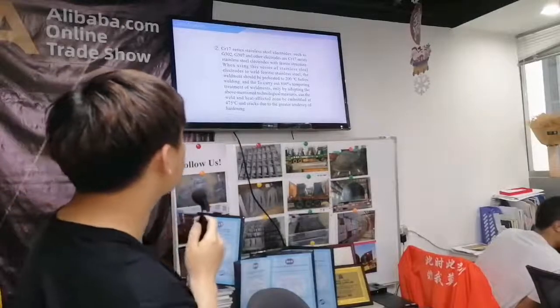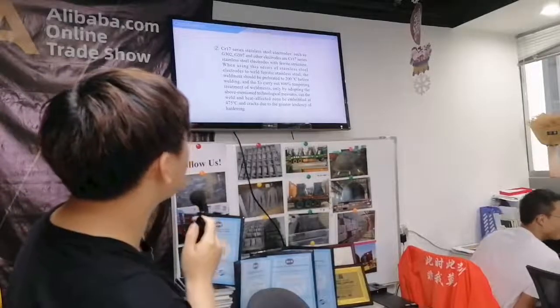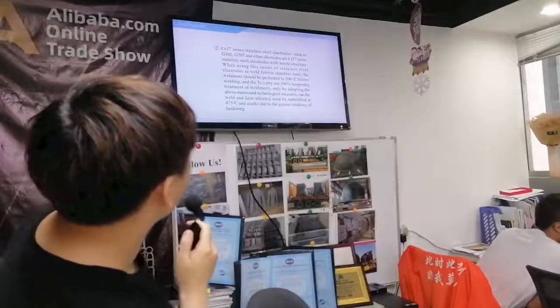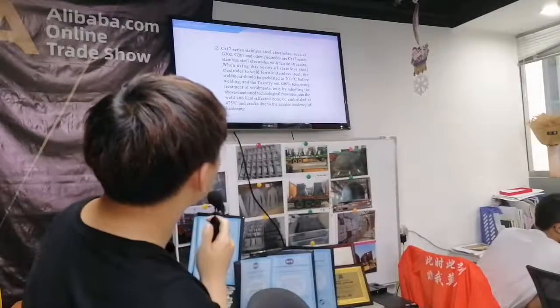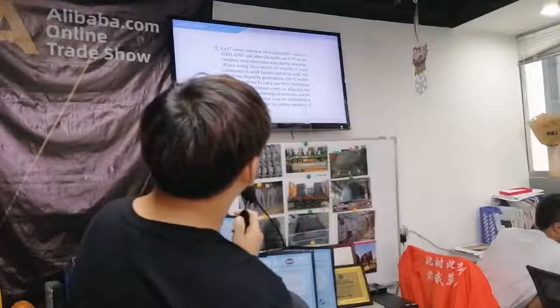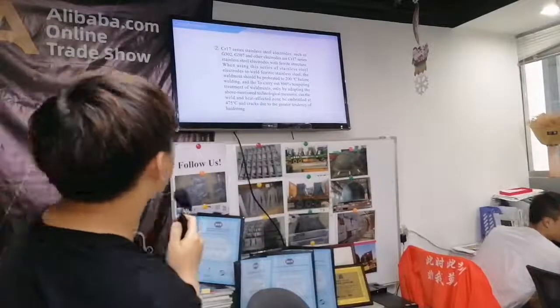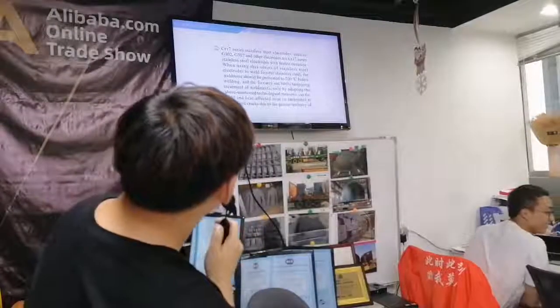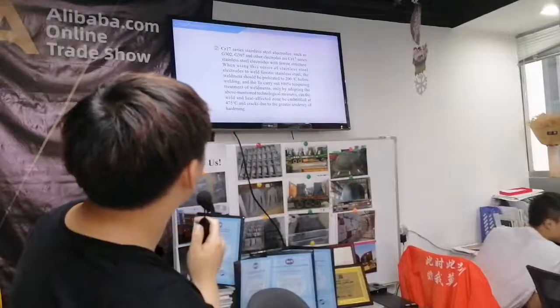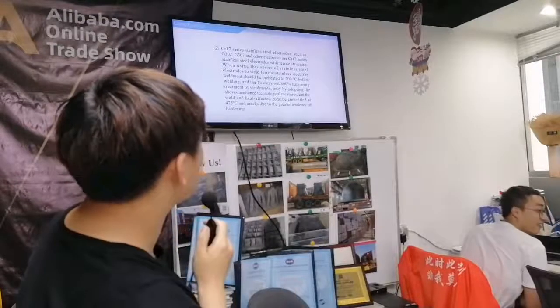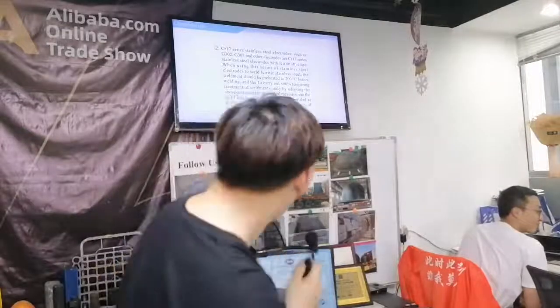Only by adopting the above-mentioned technological measures can the weld and heat affected zone be prevented from embrittlement at 475 degrees and cracks due to the greater tendency of hardening.